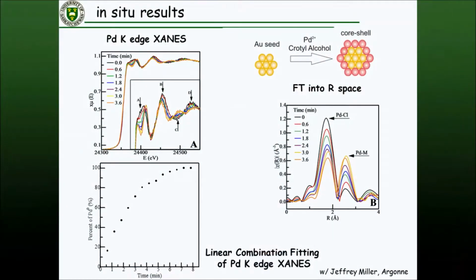The palladium K edge, and so the experiment is that I have my polymer-stabilized gold particles in water. I've added my palladium salt, and at time 0, I'm adding my crotyl alcohol to get this thing going. This was actually done in Chicago at the Advanced Photon Source. We can now do this at the Canadian Light Source as well. And effectively, at time 0, we add the crotyl alcohol, we start monitoring the reaction.